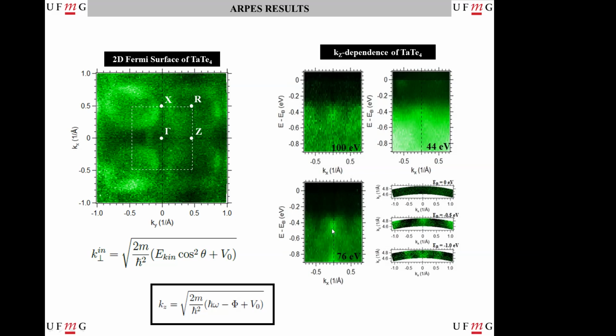But when we do cuts at 0.5 binding energy here and 1 binding energy here, we can see that we have states. And when we look at the Kz dispersion, there is no dispersion in Kz. The states look the same as we change Kz. What that means is that a 2D state doesn't have momentum in the direction perpendicular to the sample. If the states are not dispersing in Kz, they should be 2D states, which means that these Dirac cones are 2D states, as in the 2D Fermi surface, which classifies it as a topological material. Actually, this is not a topological insulator, it's called a topological semimetal.